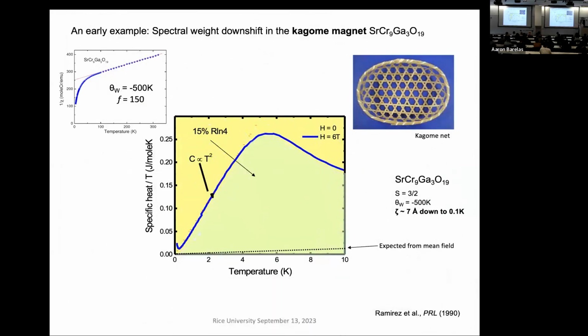And so here's an example of one of the best known Kagome magnets. A Kagome lattice is a lattice of corner-sharing triangles in 2 dimensions, and that's where the word comes from, basket weaving. And this is an example, this compound strontium chromium gallium oxide has an extremely high Weiss constant, 500 K. So if you had the same spins with the same interaction on a square lattice, it would have ordered all the way up here.